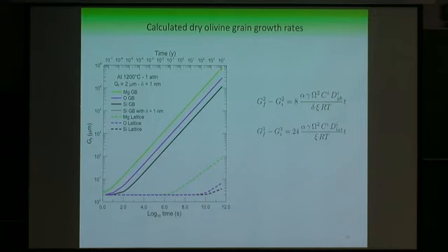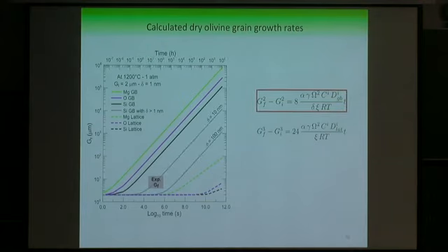And so to know which kind of diffusion coefficient I should be using, so namely whether it's grain boundary or lattice, I've added in this plot the experimental grain sizes, the final experimental grain sizes that were determined for these conditions here. And as you can see, none of these fits correspond to the experimental grain sizes. So I've assumed that the grain boundary width must have another value.